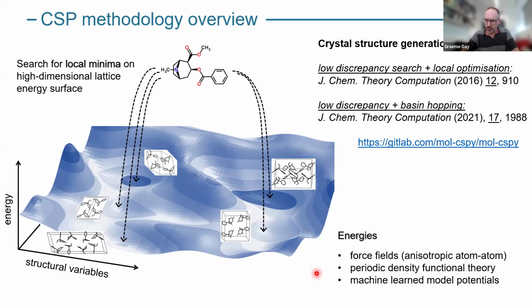The other side of things, apart from the search and the initial structure generation, is how we evaluate energies. Most of what we do needs to be very quick, so we rely on interatomic force fields, so we can evaluate the interaction energies between atoms very quickly. These are not off-the-shelf force fields. They need to be better than that. In terms of improving accuracy, what we've brought in is anisotropic atom-atom interactions, so that the way that atoms interact between molecules depends not just on distance, which is what you find in typical force fields, but also on the relative orientations of those atoms. This can pick up directional effects of intermolecular bonding between molecules.